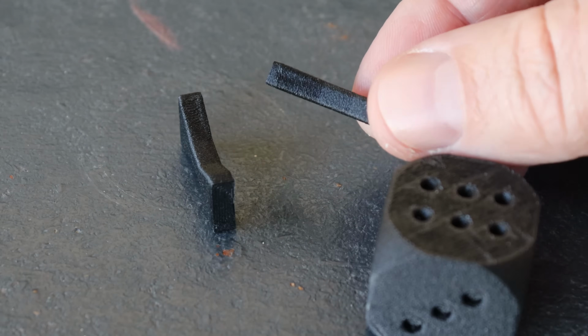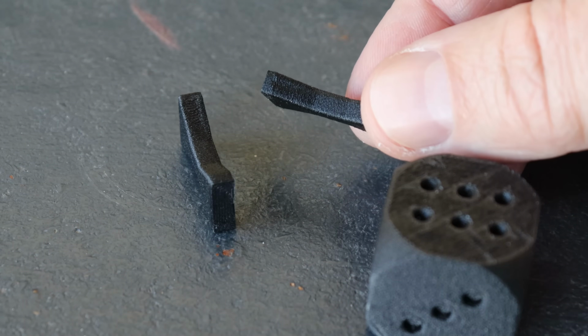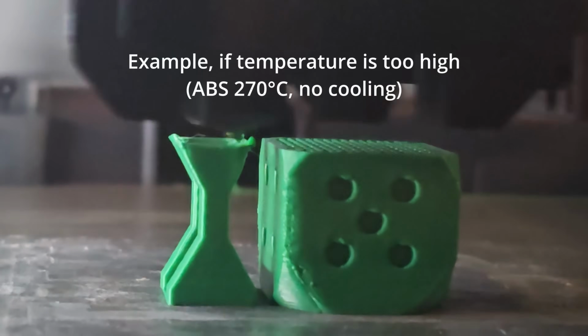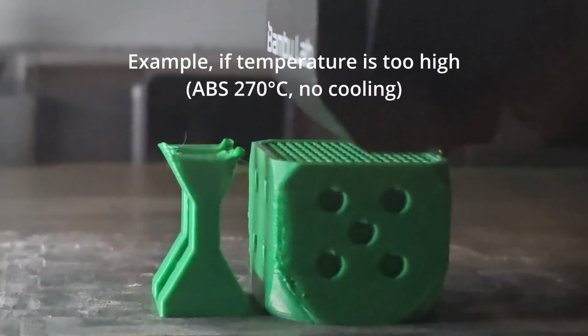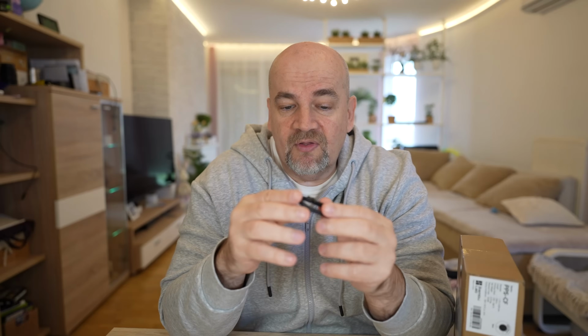Conclusions. Well, more or less what I expected. I was curious how much weaker the layer adhesion would be, but maybe thanks to these carbon fibers we can compensate for it by printing at higher temperatures or reducing the part cooling and similar, because with the carbon fiber version I can do it, but with the regular version of the ASA I couldn't go much higher with the print temperatures. Another disadvantage is that this is more brittle material compared to the regular ASA, but it is stronger, stiffer in X and Y direction, less shrinking, better resistant to bending, and a more temperature resistant material.